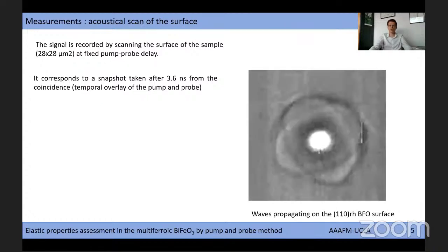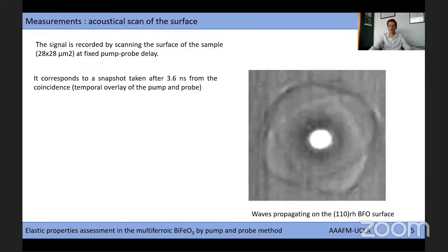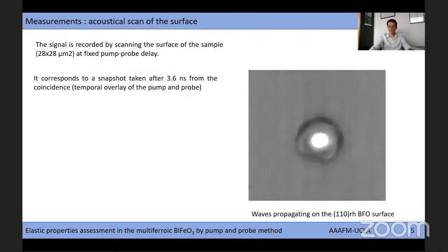This figure shows the propagation of the acoustic wave on the bismuth ferrite surface. The signal is recorded by scanning the surface of the sample at fixed pump-probe delay. It corresponds to a snapshot taken at 3.6 nanoseconds from the coincidence. The white area in the center of the image is a stationary photothermal component, and the contrast in intensity corresponds to maxima and minima in the amplitude of the waveform.